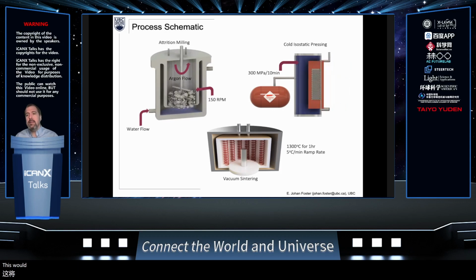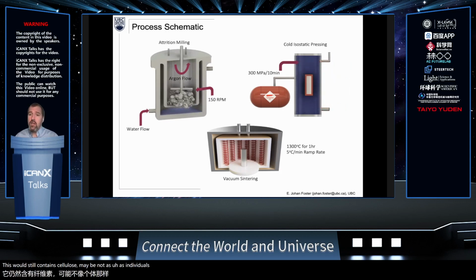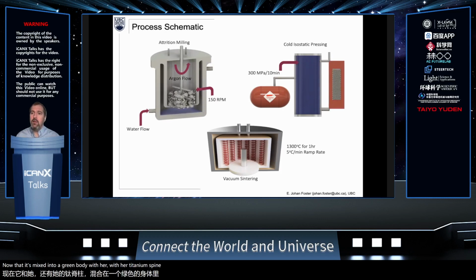So this would still contain cellulose, maybe not as individual rod-shaped objects. But then the key part here is heating this to 1,300 degrees Celsius for an hour. So me, as an organic chemist, as a polymer chemist, when we talk about high-end, high-temperature materials, think something like polyether ether ketone, a fantastic polymer that is stable up to 400 degrees Celsius. That would be the higher end of polymers. Cellulose doesn't last that long, and we're heating this to 1,300 degrees. So what does our cellulose nanocrystal, that rod-shaped filler, now that it's mixed into a green body with our titanium, do as we start to do this?